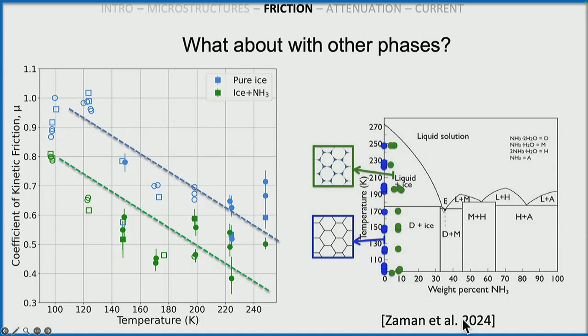So here, let's see. On this side of things, this is actually solid. And we still see a reduction in friction from the pure ice stage. But then we also see continued reduction of friction where it is a partial melt phase. But we don't see a total plummet of the friction. We're still pretty high up here. And I think that's important too.